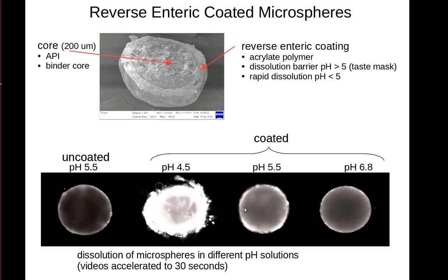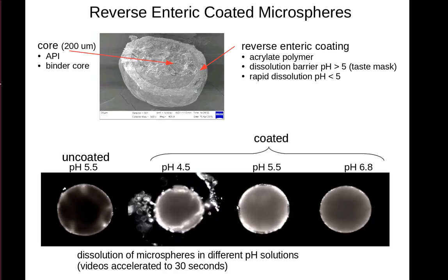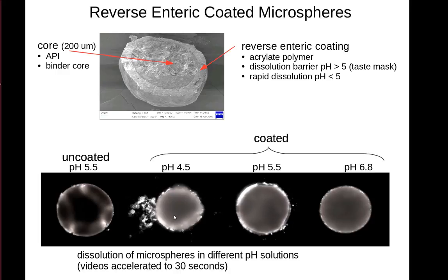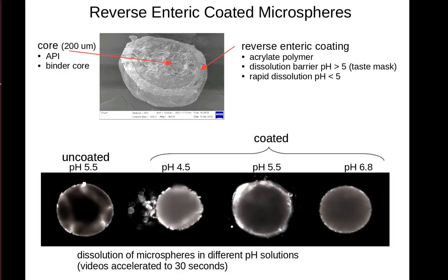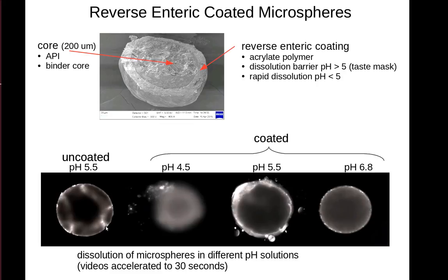The following is a time-lapse video of approximately 15 minutes condensed down into 30 seconds. Again, at 4.5, or stomach conditions, the polymer dissolves rapidly, releasing the underlying core. We can see in that same time frame, the core does undergo substantial dissolution. You can see apparently some of the API coming out through cracks.